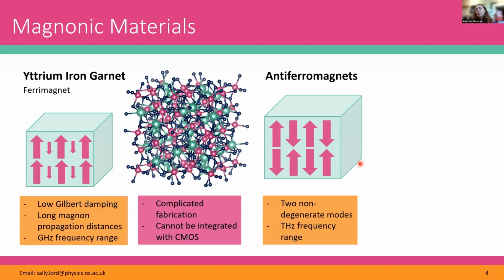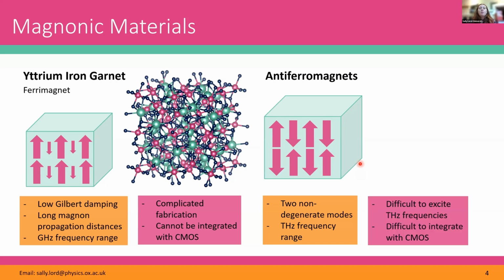Number one, they have two non-degenerate modes, which means there is an additional degree of freedom with which you could encode information. And number two, their frequencies are in the terahertz range, which is really good for computing because it would enable faster writing speeds. But it's actually also the main drawback to antiferromagnets because terahertz frequencies are very difficult to excite. And therefore, it's difficult to integrate them with existing CMOS technologies.